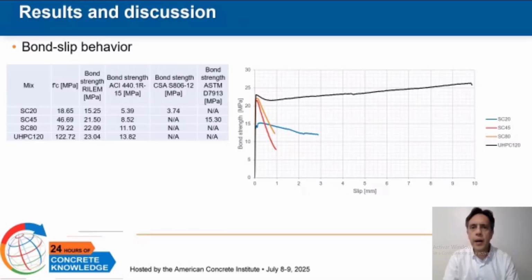This slide presents a combined view of the bond slip behavior of GFRP reinforced specimens and the corresponding bond strength predictions based on different design standards. On the right, we observe the experimental bond slip curves obtained using the Riley RC5 test, which captures the service-like bond behavior under bending. As seen, bond strength and post-peak response varied significantly across mixtures.